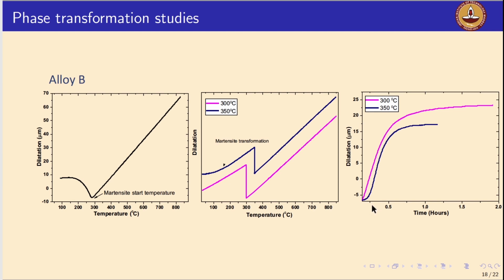So what it shows is the dilatation as a function of the time of holding at these temperatures. So the bainite transformation completes in about an hour, right? So this is an ideal condition, isn't it? If you look at the actual microstructure, what we are aiming for, the bainitic microstructure with retained austenite, can be ensured in this thermal cycle.